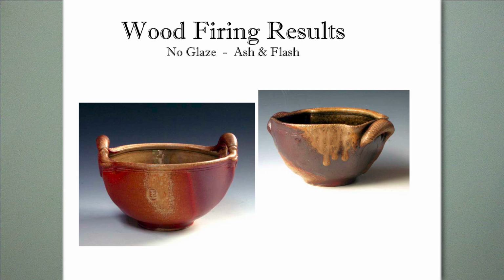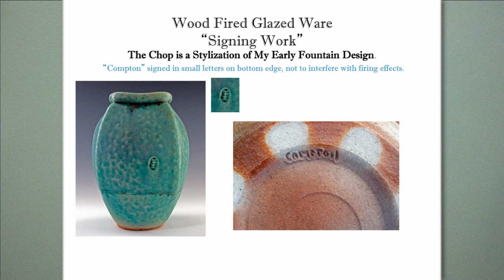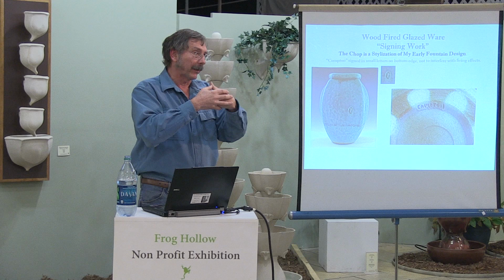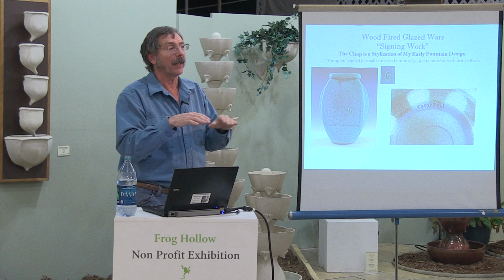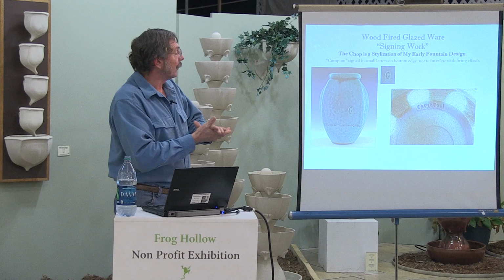I mentioned this in one of the other talks, but I'll mention it again. The pot on the right here came out of my wood kiln, but it was sitting on wadding, which keeps the pot from fusing to the kiln shelf. If you don't know what the firing process is like in wood and salt, the wood ash coming in from the flames has a fluxing action. So if you have pots in the kiln with no glaze on them, the ash hitting the pot can actually create a glaze, and you get a glazed finish, or at least a sheen. But the kiln shelves, which are made out of silicon carbide or some kind of clay material, also get glazed. And if you don't have separators, things will get fused together, so the wad marks become part of it.